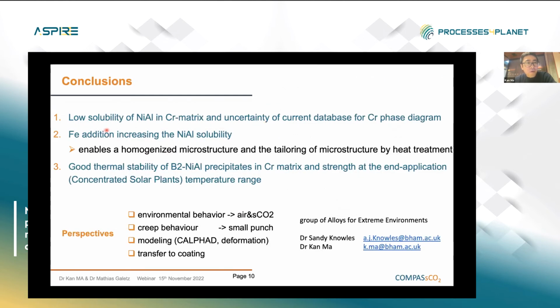So finally, for this class of material, there are some brief conclusions. The solubility of nickel aluminide in chromium is quite low and needs improvement. There is also some uncertainty in the CALPHAD database, which needs to be improved to better predict the phase diagram. Adding iron can increase the nickel and aluminum solubility, which enables a homogenized microstructure and tailoring of the volume fraction of the precipitate, which expands the design space of the material. We have also identified good thermal stability of these precipitates in the BCC chromium superalloy, and these all provide good strength for the high-end application temperature range.